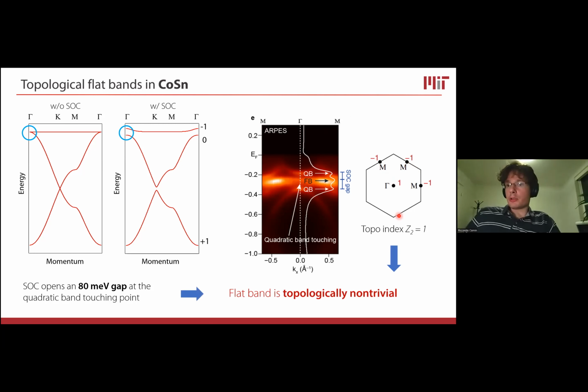And so the flat band is also topologically non-trivial, which is exactly the kind of situation that one hopes to have if one wants to realize phases that bring together topology and correlation, because really the common ingredient in the band structure of the Kagome systems that has both non-trivial topology and the ability to activate correlation effects is the flat band. Is the flat band because the flat band can be topological, as is shown here, once it's gapped out from the Dirac bands, and the flat band has a divergent density of states, or at least a very large density of states. And so being able to bring the Fermi energy to the flat band, also in the presence of topology, is exactly the place where one wants to be to realize all of these interesting phenomena that were predicted by Xiao-Gang Wen more than 10 years ago.